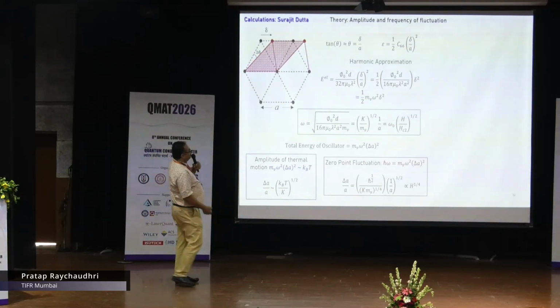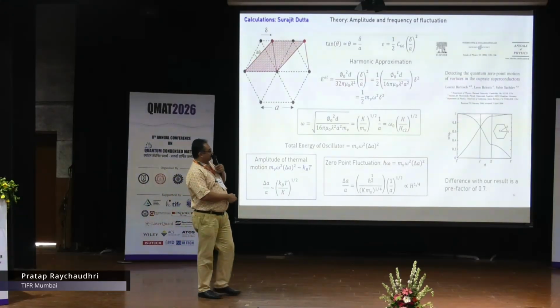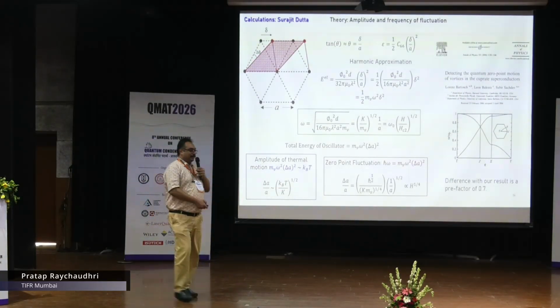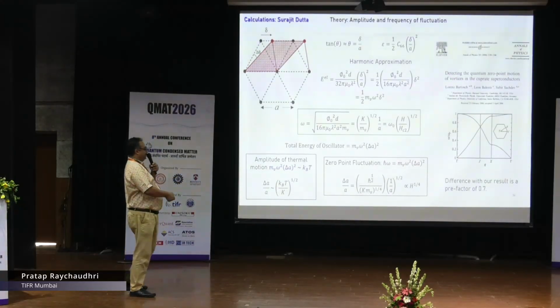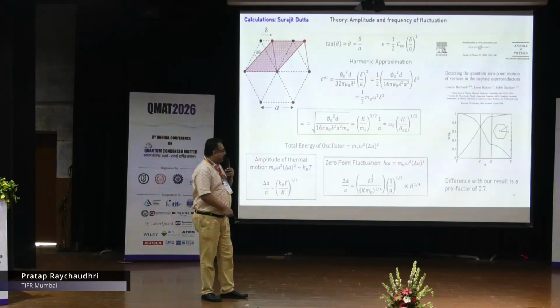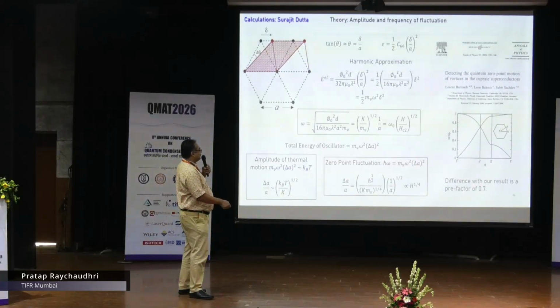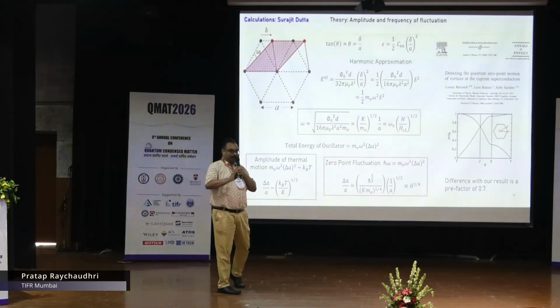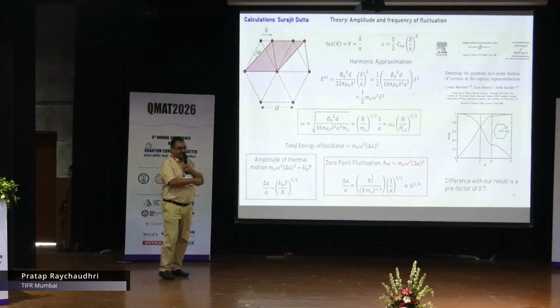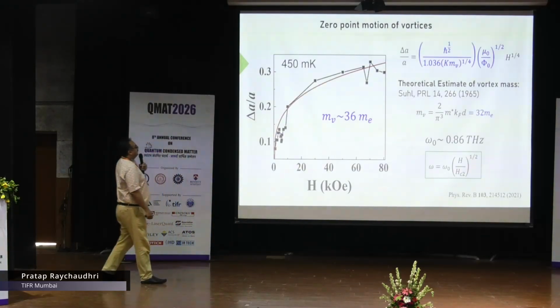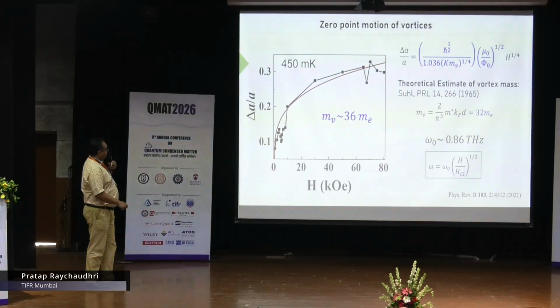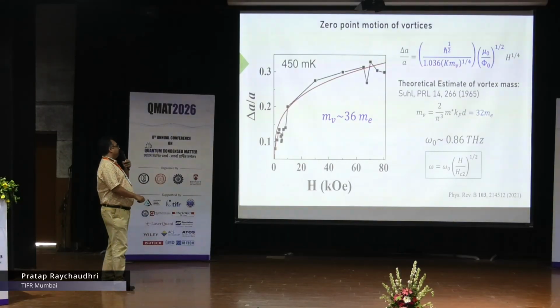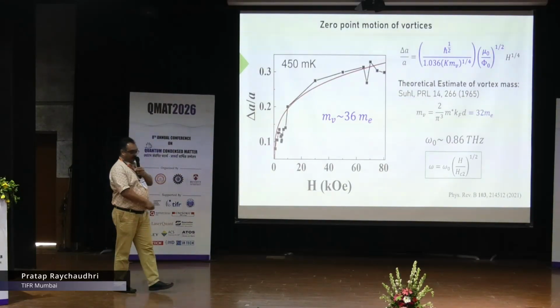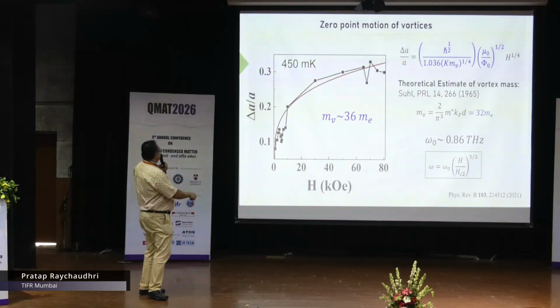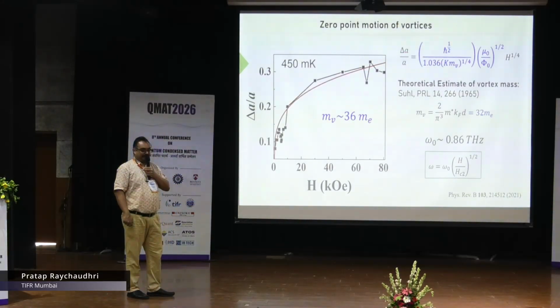Now, after doing this calculation, we realized that this was calculated by Subir Sachdev and his collaborators long back, and they had done a much better calculation than we had, taking the full dispersion relation. But the final difference in this expression was just a prefactor of 0.7. So there was no other difference from this simple calculation. This is the result. So now you can see this is h to the power 1/4. You can see broadly there is noise. These extractions are not very accurate, but it follows h to the power 1/4 reasonably well.